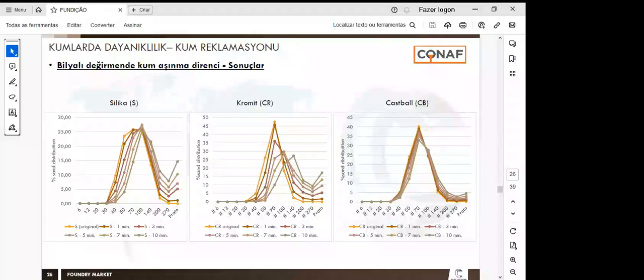Castball maintains the particle size distribution. It's very, very similar after the attrition. This result indicates that Castball presents high durability, higher than chromite and silica sand.